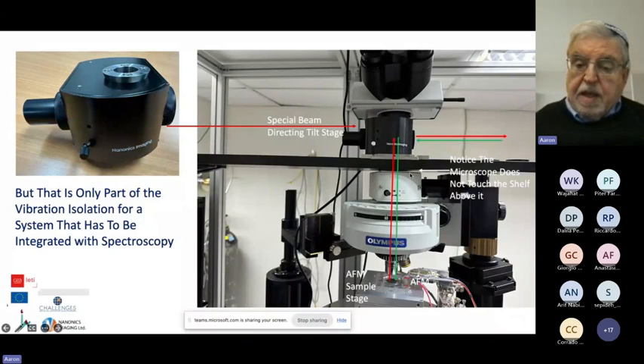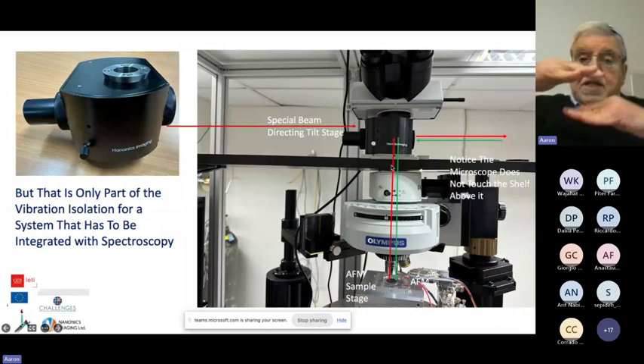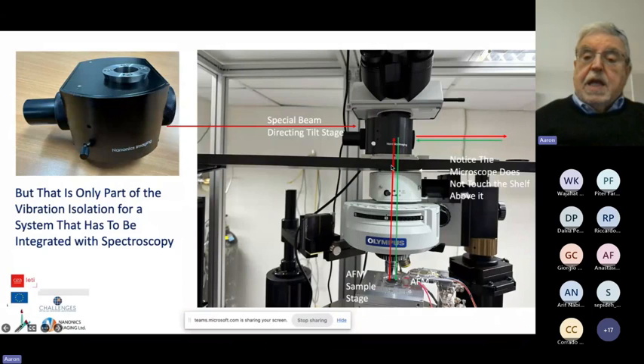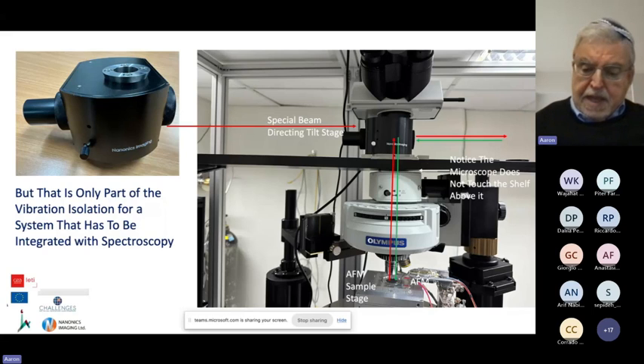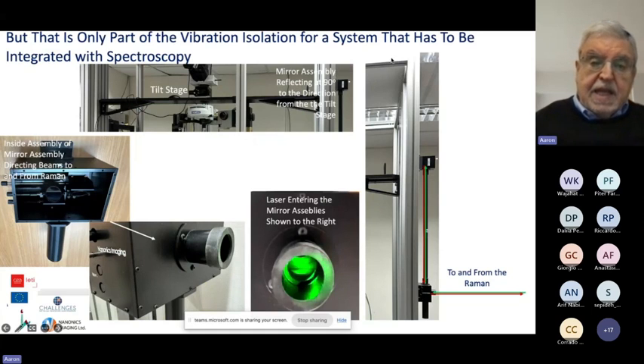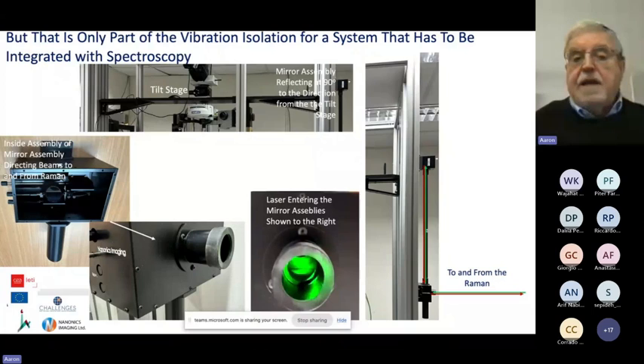If you can see, there's a separation between the optical elements here and the ocular. And it passes light back and forth. And even though there may be vibrations in this direction because of what's on the table, the lasers, the CCD fans, and so on and so forth, because the lenses are infinity corrected, you see none of that in this design. So basically what you're seeing here is the light entering the mirror assembly. These mirror assemblies are over here, and they go into this assembly, which then brings it down. And so both the light for excitation of the Raman and the light for collection of the Raman go through these same paths.